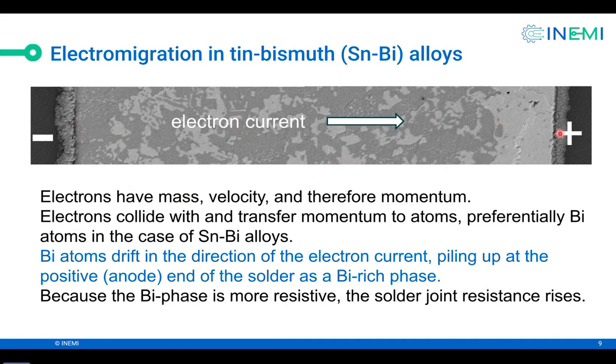So this is just one view of this planar solder. Current is flowing towards the right. So this bright region over here is the bismuth that collected on the anode side. And this gray region on the left side at the cathode is tin-rich. So basically you can see that the bismuth-rich phase has electromigrated to the right. And the reason for this is electrons have mass, they have velocity, therefore they have momentum.